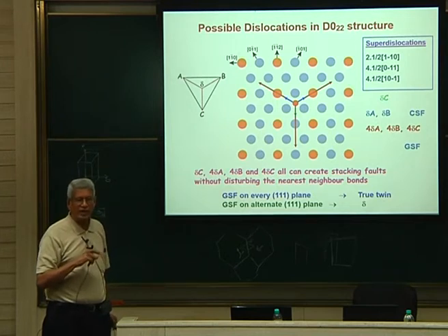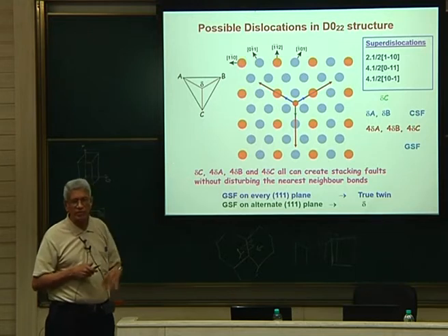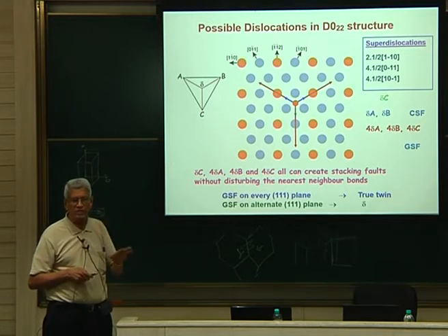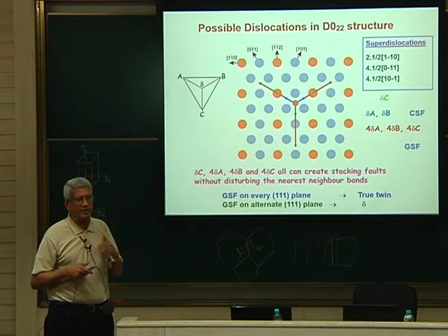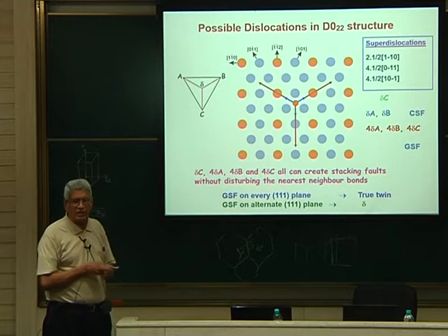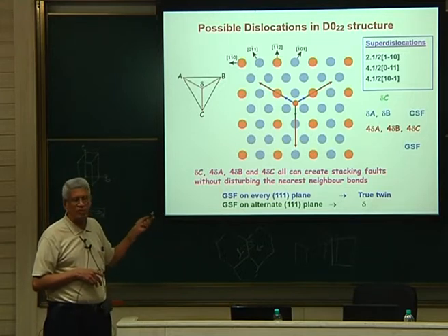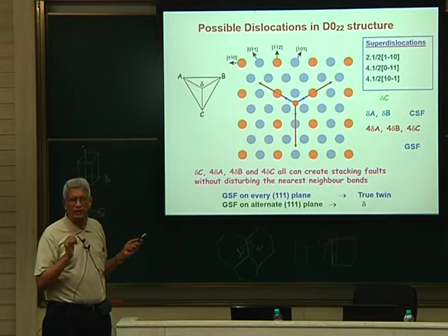In a matrix which contains all the variants, with different variants oriented in different ways, we should in fact see groups of 4 types of dislocations. So how many dislocations are necessary? Generally we say that the material is ordered if we see pairs of dislocations. That is not correct. That is only valid for particular phases. For all other phases it is decided by crystallography. If you look at the close packed plane, then we get that information about how many dislocations are required.